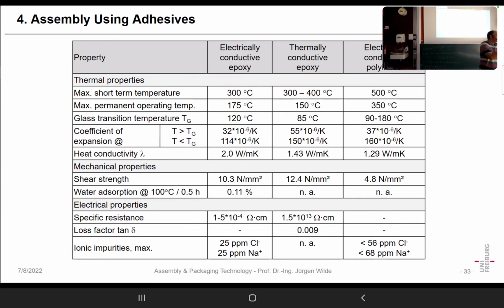The problem is more the temperature cycles, which typically lead to lower stresses. But you can also find adhesive joints which have a strength of, let's say, 50 or so. That depends on many parameters. It depends on the surfaces, on the thickness of the joint, and also on the device. Sometimes it's not the adhesive that fails, but the metal layer on the chip, for instance, peels off. So in that way, you could say that value is sufficient, but the value itself is not so important.